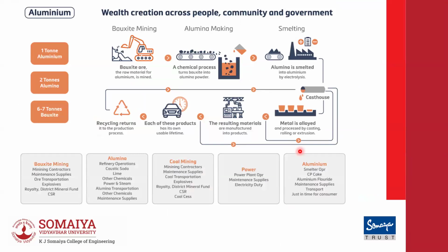Now, if you look at the processing of the aluminum ore, which is your bauxite, I need 6 to 7 tons of ore to produce 1 ton of aluminum. So you can imagine how much material is wasted. Two, what sort of process you need to do the mining? You need to make the alumina first, then you need to smelt it. Smelting is majorly done by electrolysis. In Australia, they used to have a lot of aluminum smelters, especially using the Hall-Héroult process. But then, because of the electricity cost, a lot of them have been shut down. So this is heavily dependent on the grid electricity. And as you know, electricity in both countries is carbon driven. So again, you have a contribution of CO2 over there. So again, there's a good amount of CO2 generation to make aluminum.